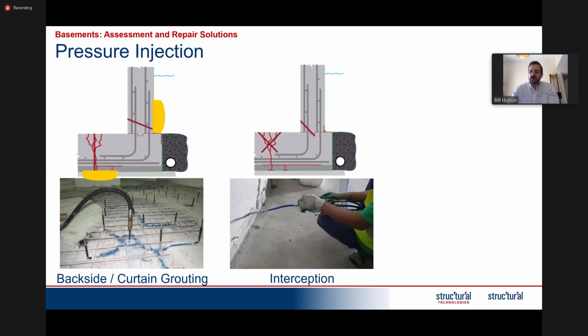Another common method of pressure injection or chemical grouting is something called interception grouting. So this is where, if you take one of the most common areas where a basement would leak, it is the construction joint between the slab and the vertical member. That's a better example. So we call that the kicker joint. That's a really common place where water can come through. So what we do is we drill in at a 45 degree angle to try and intercept the midpoint of the joint, and then we would inject the material inside to completely seal the joint.